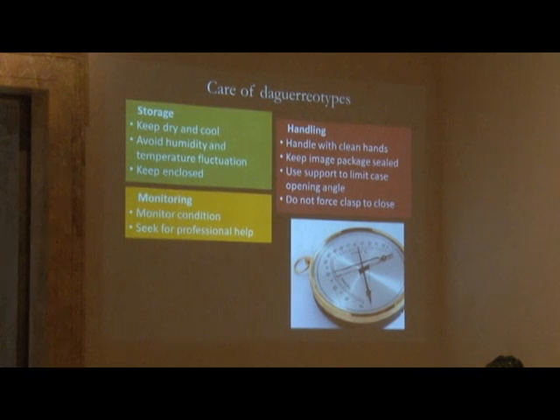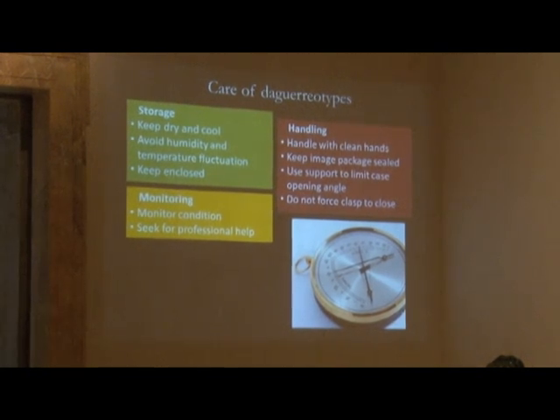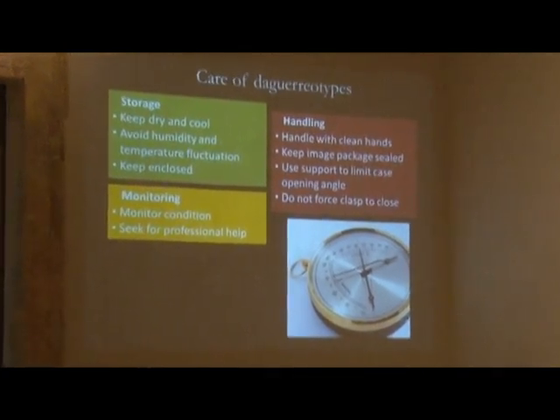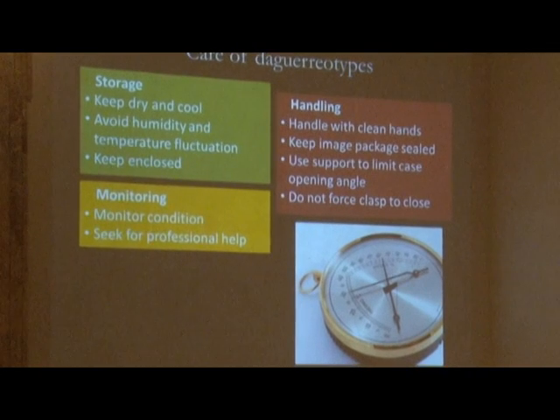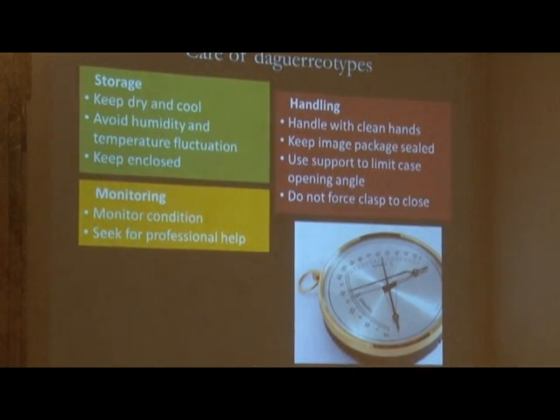To keep daguerreotypes in good condition, storing and handling them properly is very important, and I also recommend condition monitoring. For storage, I recommend keeping them in a dry and cool environment where there's as little fluctuation as possible. So avoid storing or displaying them near a heat vent or areas that get direct sunlight. A bathroom will be terrible. It has huge fluctuation in humidity and temperature. Recommended relative humidity for cased photographs and daguerreotypes is 40 to 50%, but seasonal changes are inevitable. So try to focus on minimizing the daily fluctuation as much as possible.